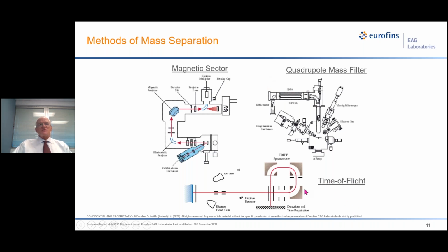In a time of flight instrument, this is basically just very different. We have a pulsed ion beam, we have pulses of ions, and when a pulse of ions hits the sample, a burst of secondary ions is emitted, and these ions are accelerated and travel in this path with these electrostatic sectors. And all the ions have the same energy. So the lighter ions travel faster than the heavier ones. So if you simply time from the input pulse when the ions are made until when the ions hit the detector, you can calculate the mass.